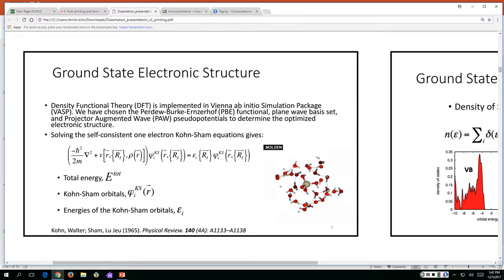Will it be possible to generalize and tell that there is a class of states or class of excitations where spin polarized and spin orbit qualitatively coincide, and then we can reduce computational cost and do everything with spin polarized? It will be very pleasant, very helpful, but hard to believe. At least in this specific case they coincide, and if you would have more states, we could prove a theorem like: forget spin orbit, do the old good spin polarized.